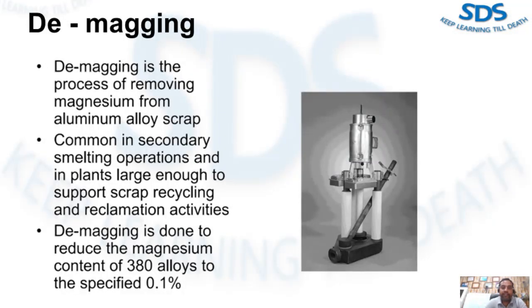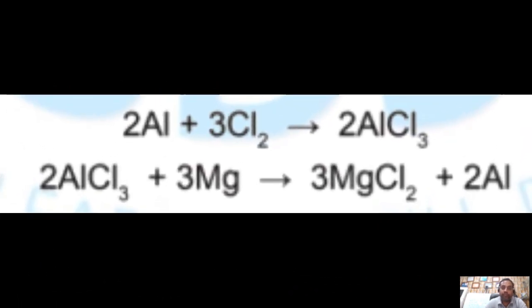Chlorine and fluorine. Magnesium removal from aluminum is accomplished by application of chlorine or fluorine compounds which react favorably in aluminum according to the following equation. When chlorine gas Cl2 is introduced into liquid aluminum, it reacts to form aluminum chloride AlCl3. The aluminum chloride reacts with magnesium to form magnesium chloride MgCl2 and aluminum. The magnesium chloride then flows to the top of the metal bath and is removed in the dross. Aluminum acts solely as the carrier for this reaction.